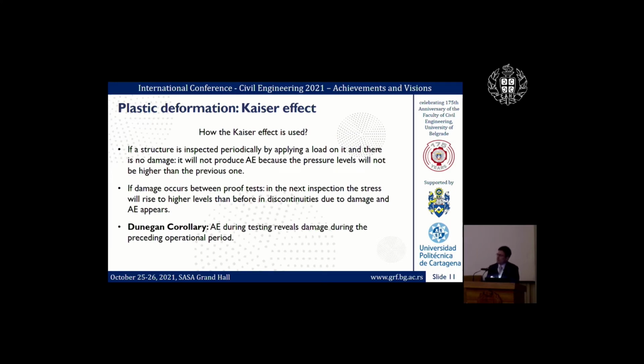Well, how can it be used to inspect a structure? What you have to do is inspect your structure regularly, in between several periods of time. If there is no added damage in that period of time, then we are not going to measure any acoustic emission. But if you receive acoustic emission, what does it mean? It means that some kind of damage has occurred during that period of time, and there is some discontinuity in the structure, in the mesh and the material, and then the concentration of stress is going to produce an acoustic emission that you are going to measure with your sensor. This is what is called the Kaiser effect, that is, the acoustic emission testing reveals damage during the preceding period.